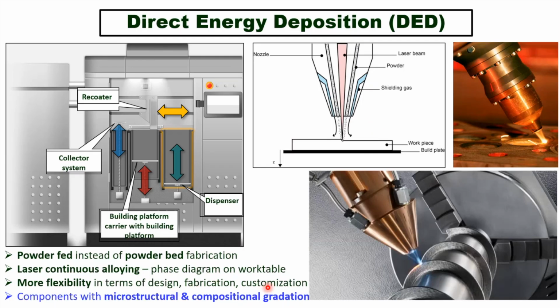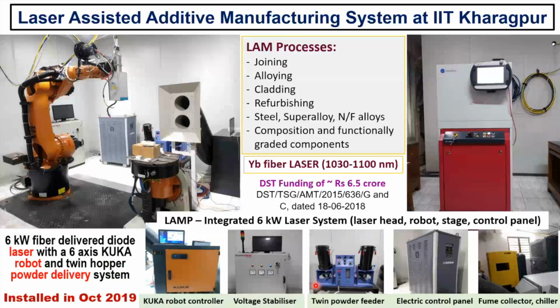The biggest advantage of this direct energy deposition approach is that you can play a lot more to modify or tailor the microstructure and composition, making them even graded and creating very many interesting components and structures. So this is what I mentioned at the beginning — with generous funding from the Department of Science and Technology in India, we were able to establish a 6 kilowatt, 6-axis robot-delivered powder delivery system in 2019.